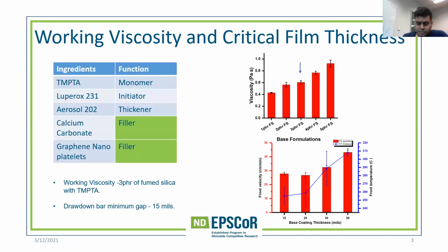The important aspect in frontal polymerization of coating was to select a working viscosity so that the films are drawn and they don't flow out, or the resin is not too thick that we are not able to draw the films. And also we need a critical film thickness so that the front propagates neatly and cleanly. It doesn't stop in between. For that, the monomers we used are TMPTA, as I mentioned, and initiator as Luperox 231.